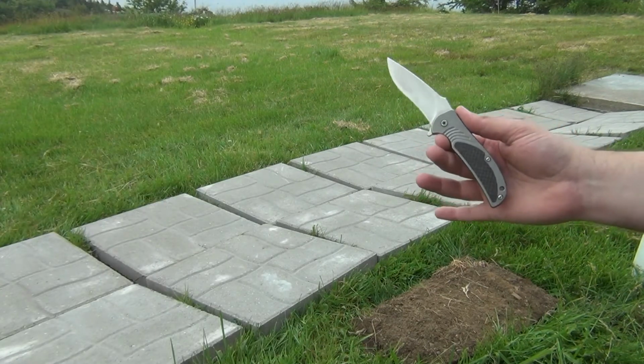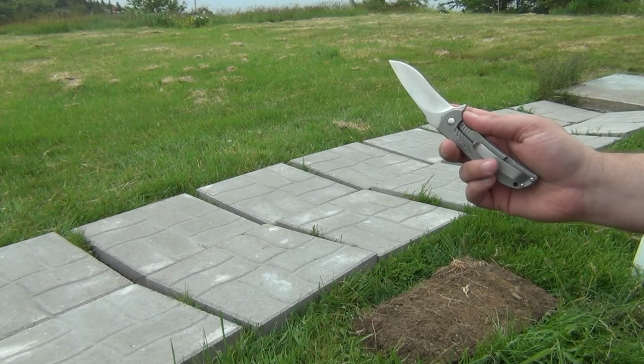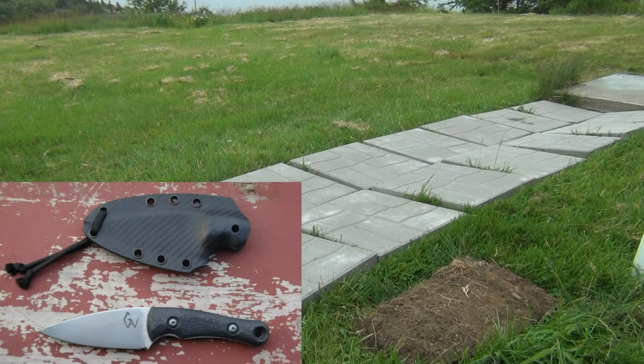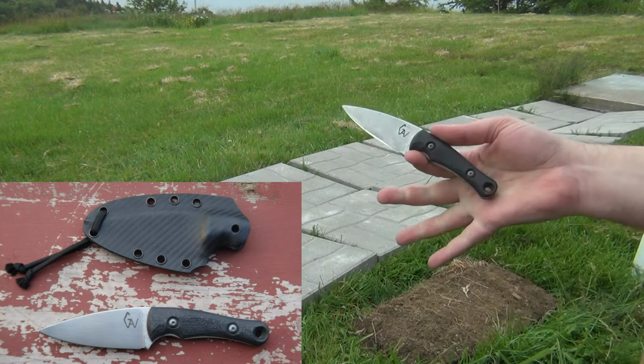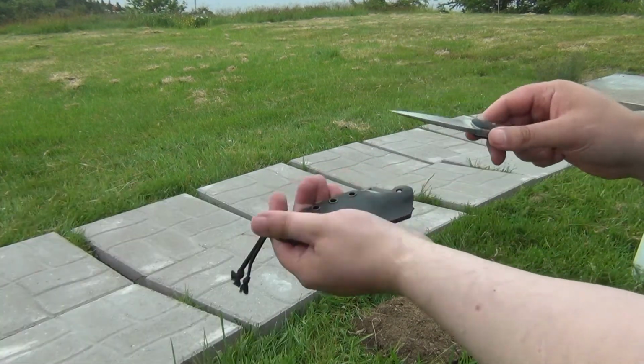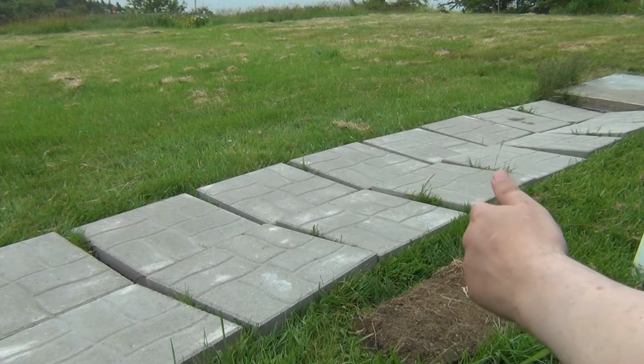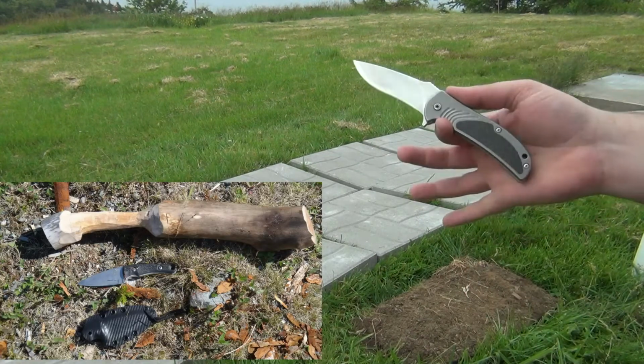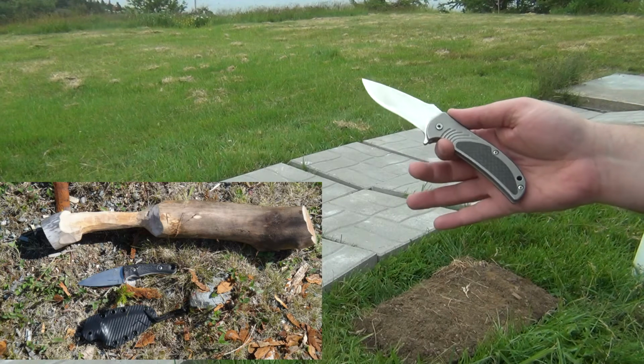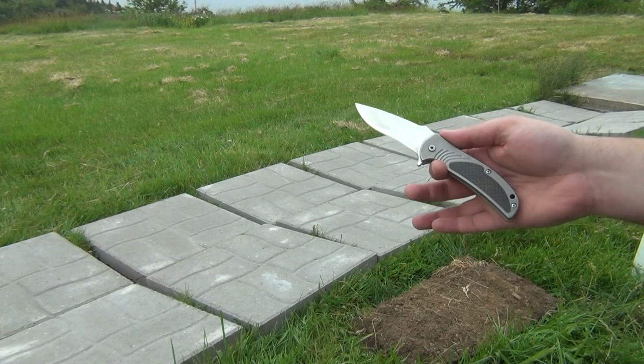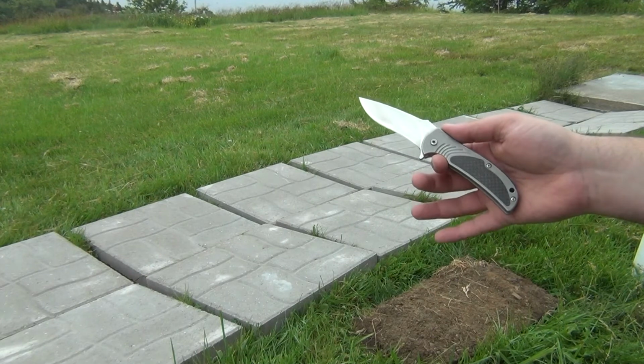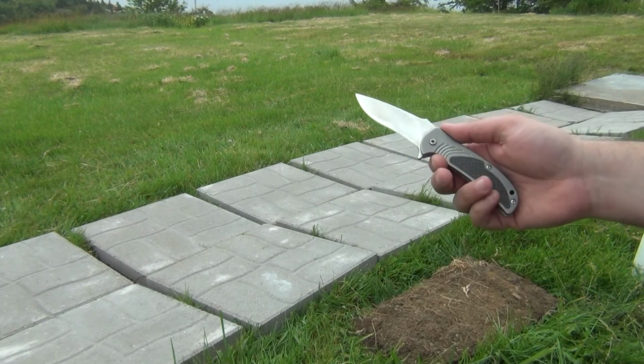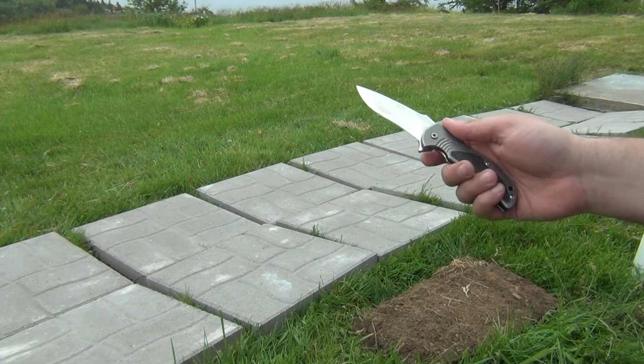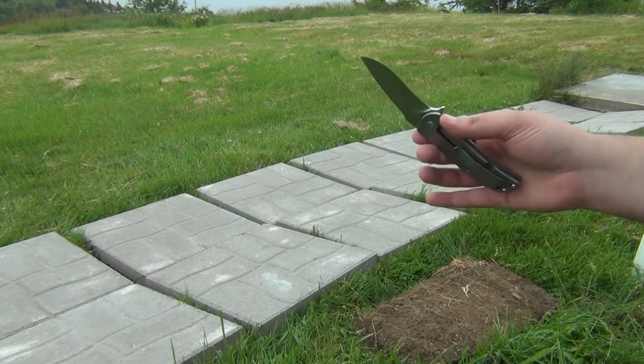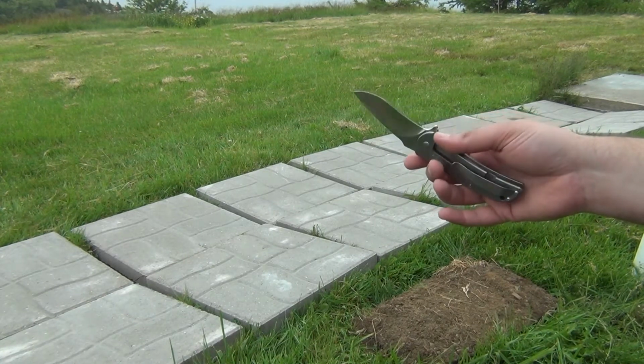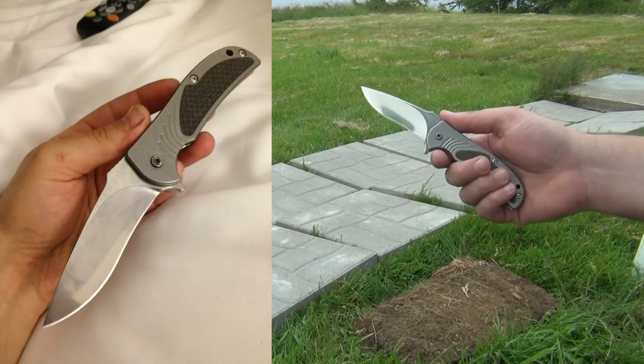One of the reasons why I got this model is that it's in S110V. I have a blade in S125V from Mike, so it'll be interesting to compare those two steels. S110V is an interesting evolution of the 420V family of steels. Lots of information in the patents on those two steels, or families of steels rather. Again, that's in the description. But basically what they did is they replaced some of the vanadium with niobium, and they increased the amount of cobalt that was in the steel.